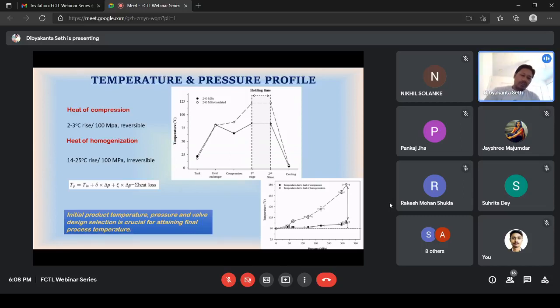The purpose of showing this is that we need to design our system in such a way that we achieve a predefined temperature. Suppose we are targeting the killing of the spore formers. Nowadays with high pressure homogenization, people use temperatures up to 140, 150 degrees Celsius. But the recent advancement is that even at a 110 or 105 degrees Celsius rise, we could achieve the killing of the spore formers. But also it depends on the types of the spores and all these things.